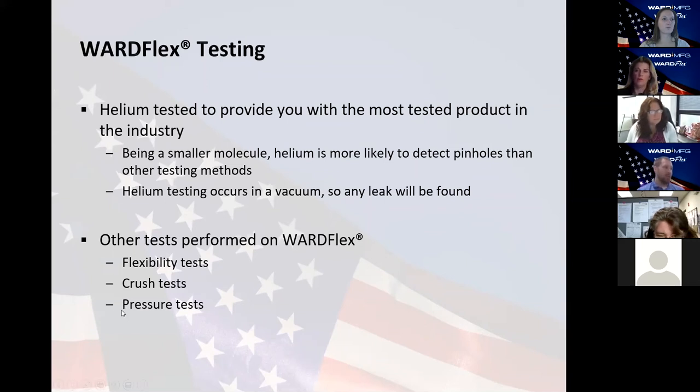And then the other test that you saw there, the pitch check, that happens 100% as it's going, and on each drum. The hardness test, again, that happens every day. And then the other tests there happen on a quarterly basis, and that's prescribed by the ANSI LC1 standard. So we make sure we at least follow the minimum requirements there. On many of them, we're doing it on a monthly basis, so we're exceeding that requirement.